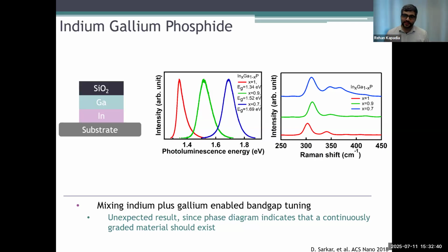So we did this experiment because we were fully expecting to get graded materials where we had gallium phosphide on one side and indium phosphide on the other side. And we actually found that that was not the case. What we realized is that if we were able to push the growth fast enough, we were able to move away from that thermodynamic limit, and we were able to be a little bit more kinetically driven, and that then allowed us to get compositions in the solid that were closer to the compositions in the liquid, instead of what we would expect from a fundamental thermodynamic analysis.